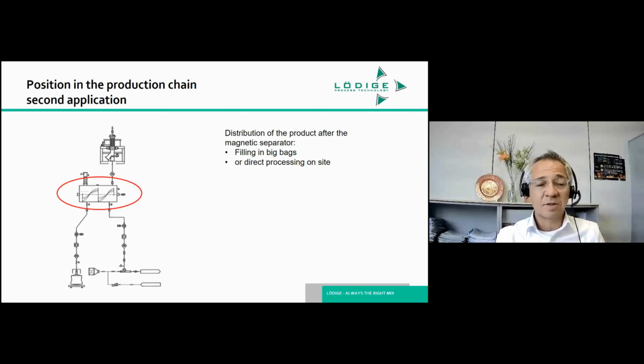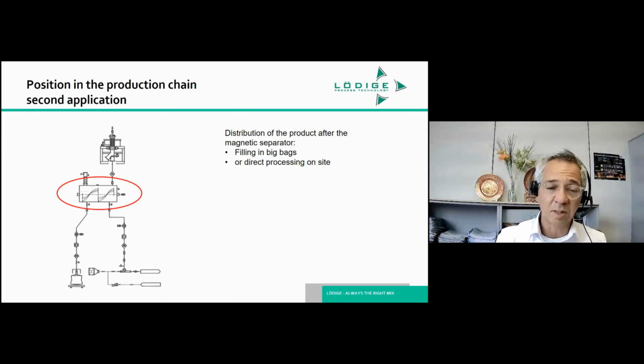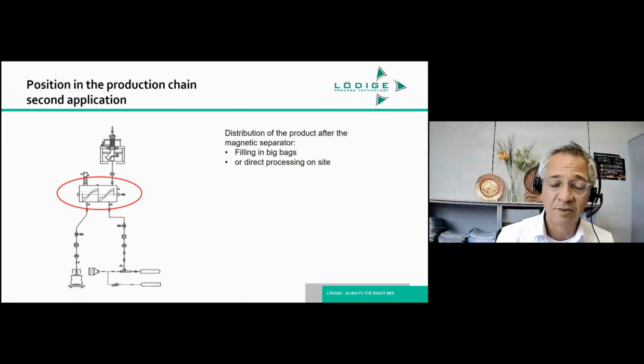The battery mass production, as I say, has various steps. And up front, there is a mixing step where you have high-speed mixing using plowshare mixing equipment, relatively intensive mixing. But then downstream, you also have another step where mixing equipment or blending equipment is employed. And this is after the magnetic separation. Reason being is that during the course of the post-treatment after the first mixing step, you do get fluctuations in physical product qualities, that you can negate and equalize by using a post-blending step after the final magnetic separation.